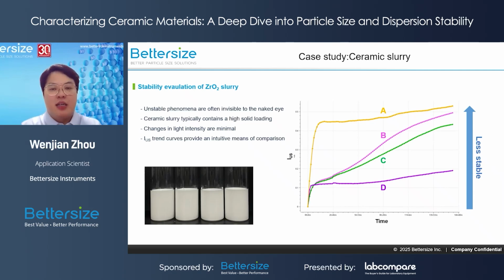In fact, no changes could be observed with our naked eyes. In this case, we need to ask Turbiscan Lab for help. In most cases, slurries are highly viscous since their solid loading is very high. The samples are concentrated and opaque, so we rely on backscatter signals rather than transmit signals.